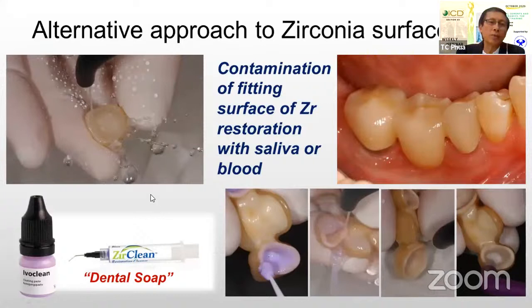wash that off, and that will give you a very clean surface for you to prime your zirconia. Remember, for zirconia surfaces, never, never clean it with phosphoric acid, because that poisons the surface, and you will not be able to put zirconia primer, which essentially has MDP in it, because it will block all the sites for the MDP to bond onto.